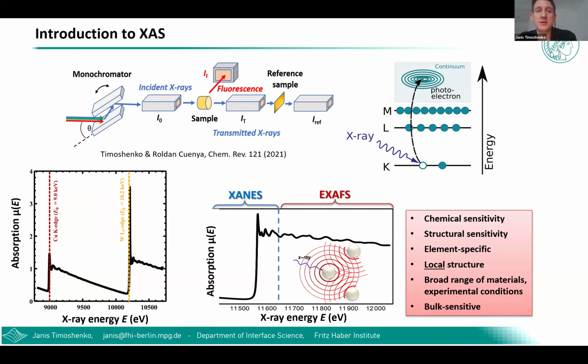In general, X-ray absorption spectroscopy is a local structural investigation method which provides you with information about the local structure, so the electronic structure and atomistic structure of the material. Typically, we distinguish two regions here: the X-ray absorption near-edge structure and the extended X-ray absorption fine structure, so XANES and EXAFS, which encode information about the chemical state of your catalyst and its atomistic structure respectively. Both these XANES and EXAFS regions will be useful for our discussion in the next slides.